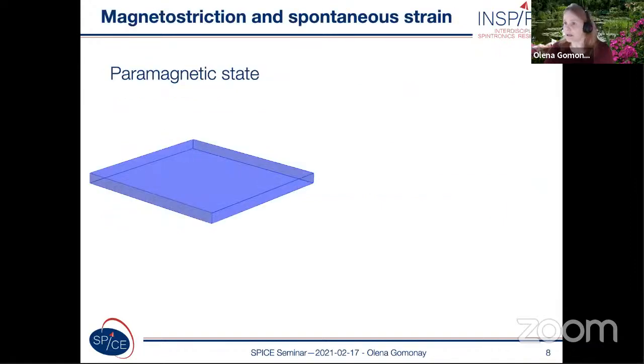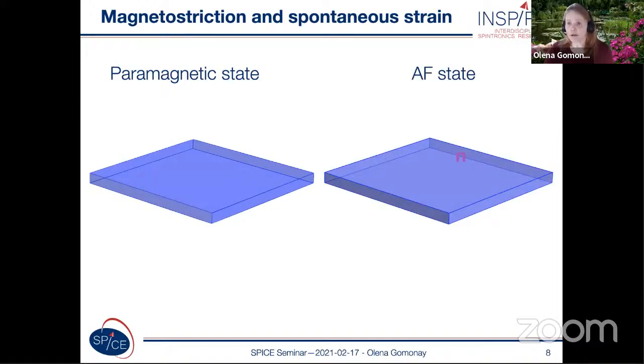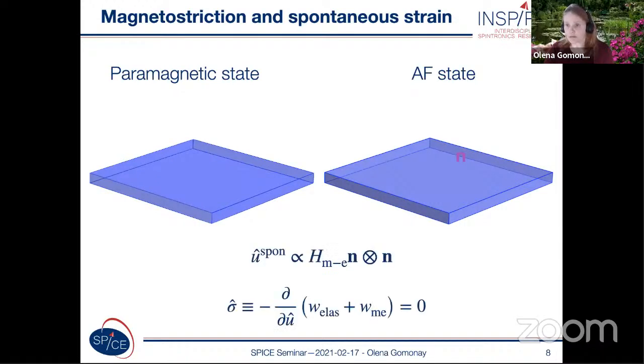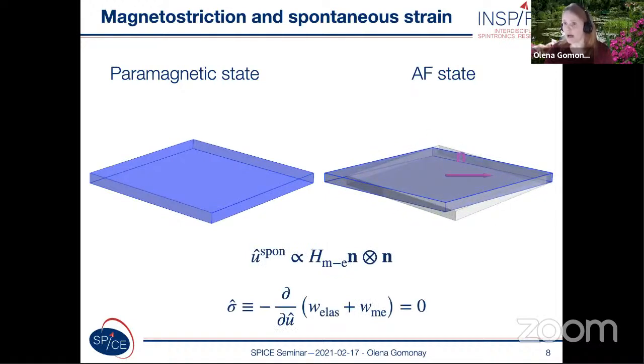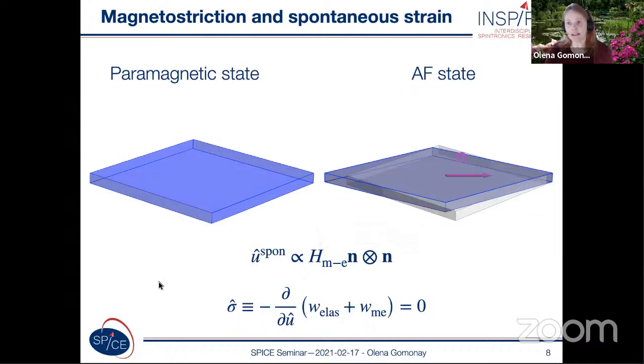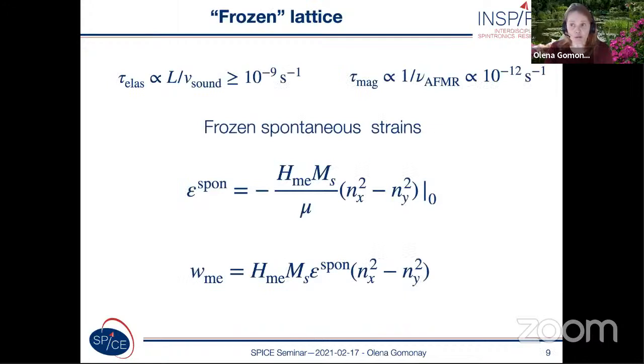So let's consider an antiferromagnet which in a paramagnetic state has a tetragonal lattice. When it goes through the Néel point, the lattice tries to deform, and the corresponding deformation is associated with the orientation of the Néel vector. And if this antiferromagnetic sample is homogeneous and infinite, we call the corresponding deformation spontaneous strain. And this spontaneous strain corresponds to the condition of the stress-free sample. Though spontaneous strains map the distribution of the Néel vector, and they look like some secondary order parameter, if you wish, they can play a very important role in dynamics.